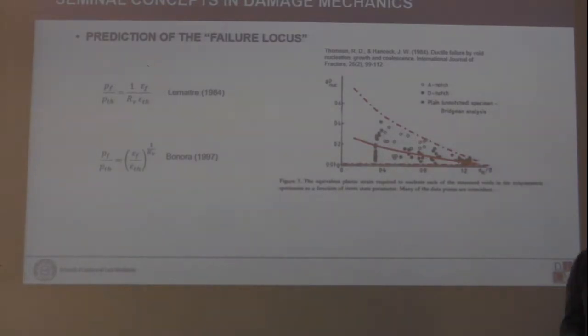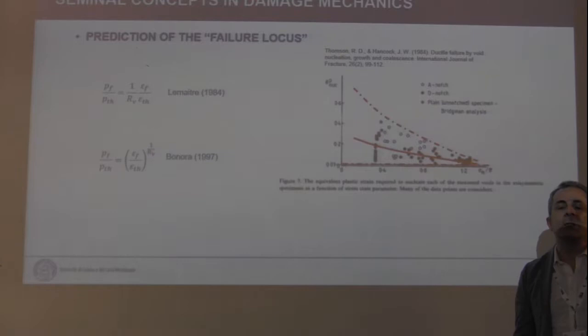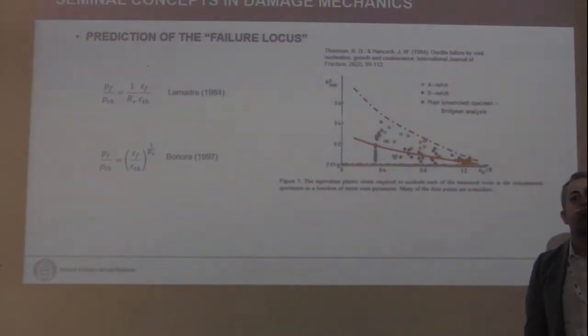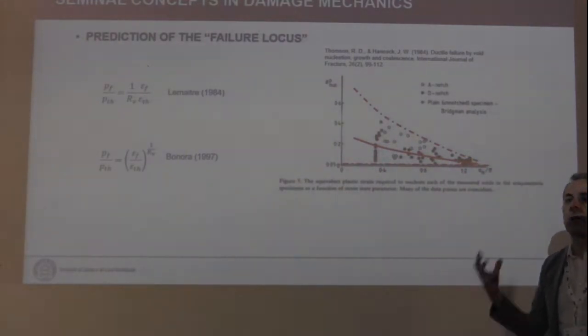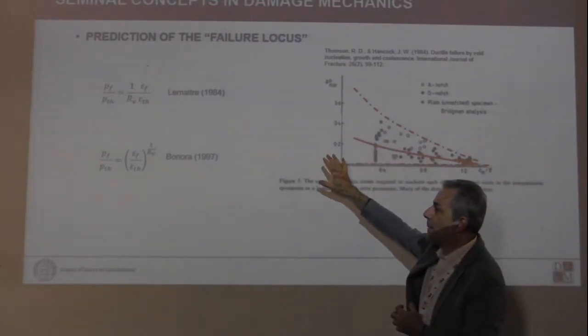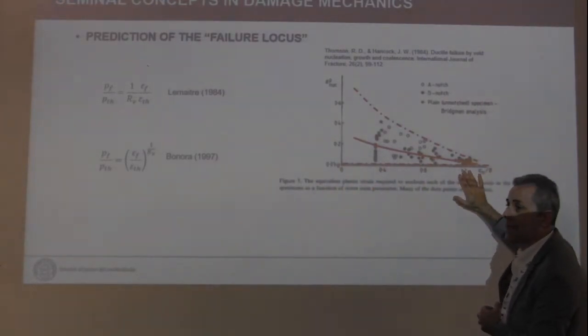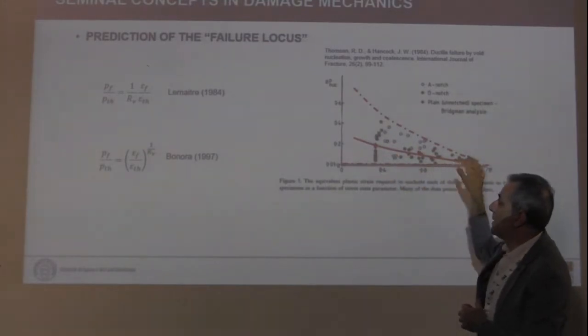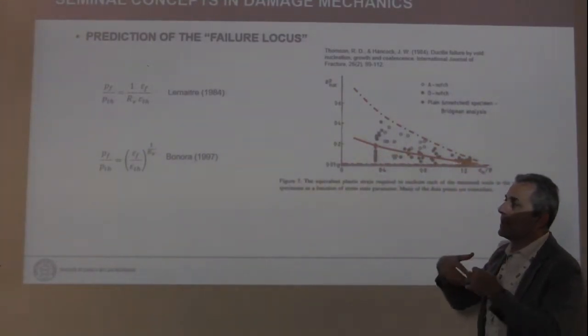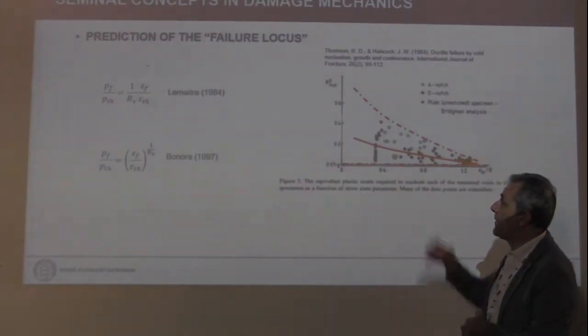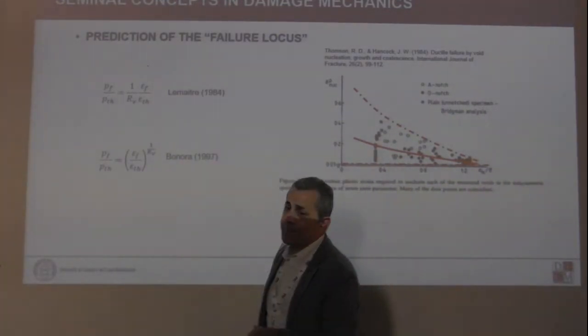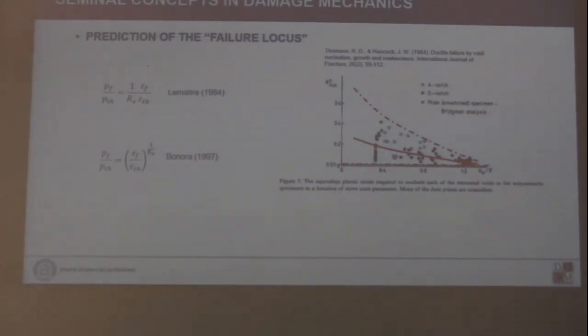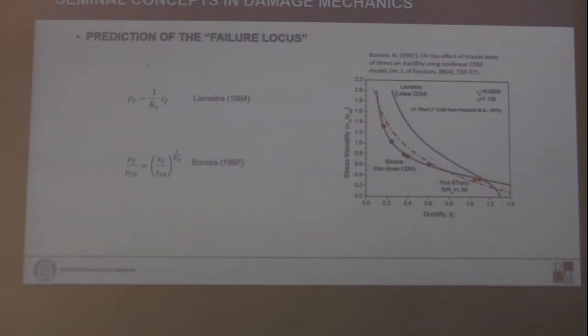Another very important and seminal concept is the fact that if we have the effect of stress triaxiality embedded into our formulation, we can predict the so-called failure locus without the need of additional hypothesis. The failure locus is the place on a plot where we have the strain to failure as a function of stress triaxiality, and this place is theoretically predicted and can be verified by experiments. In particular, there are different solutions in the literature, and of course you can validate this comparing with experiments that are usually provided with tension tests on round notched bars, and I think that this is one of the key points in the very big value offered by damage mechanics.